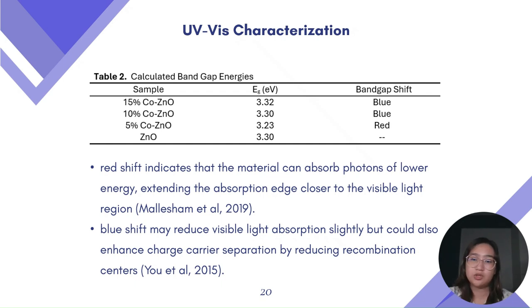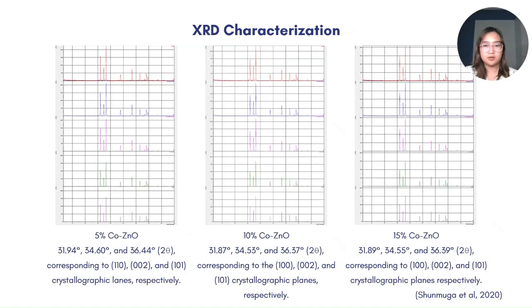At higher cobalt doping concentrations, the blue shift or slight bandgap widening observed suggests a partial restoration of the intrinsic ZnO band structure. The shift may reduce visible light absorption slightly but could also enhance charge carrier separation by reducing recombination centers associated with defects present at lower doping. The improved crystallinity or reduced defect density at higher doping levels can lead to longer-lived charge carriers, which is critical for efficient photocatalysis. However, excessive doping can lead to clustering or secondary phase formation, which might adversely affect photocatalytic activity by acting as recombination centers or blocking active sites.